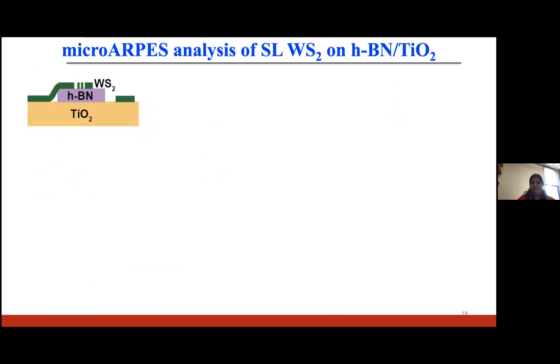So in order to study this, we fabricated a single layer WS2 sample on titanium oxide. Here's the side view schematic of my sample. We have a single layer WS2, which was a CVD grown sample, and it was transferred on HBN, which was sitting on a titanium oxide substrate. Once again, this titanium oxide substrate is n-doped, so it's conducting. And just to make sure that we don't have any charging effects, we drape our WS2 sample around the HBN so that it's touching the conducting substrate.